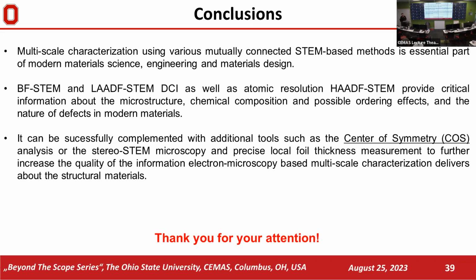We've seen it with JP Cousinier, who was here working on BCC high entropy alloys. We were trying to image the dislocations in this very dense field of coherent precipitates, which were all scattering a lot also. So it's very difficult to image dislocation lines, and we had to play a lot with the objective aperture, convergence angles, and settings of the STEM to find the optimal conditions for that specific alloy, orientation and case. So bright field is easier; dark field, if you want nice data which you trust, is more difficult.